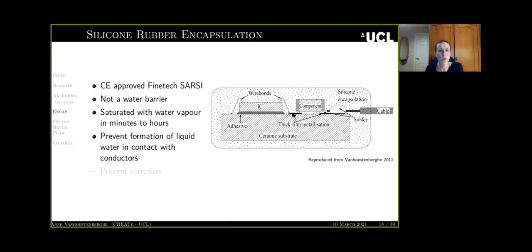We know that it will work as long as the surfaces on which it is deposited offer very good adhesion, and as long as these surfaces themselves are not permeable to water vapor. The problem then is, okay, for a metal, it works. We know that if you prevent formation of liquid water over a metal, that's fine. But when you start working with ICs, we know that the surfaces of the ICs are not finished with metals,